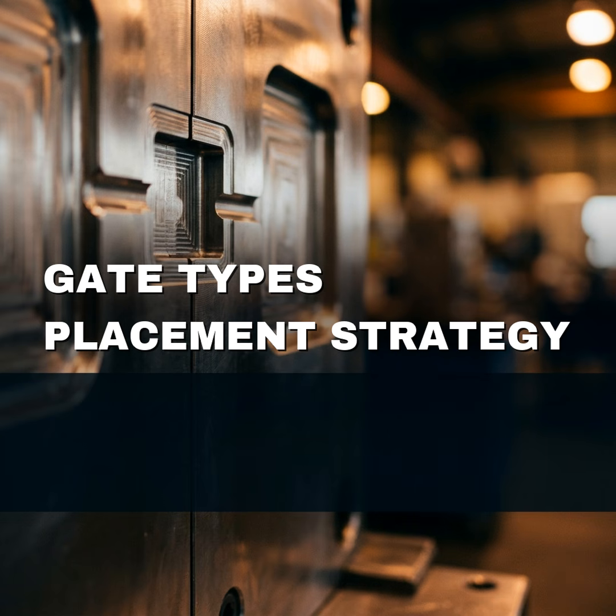We have the pinpoint gate, or just pin gate. This is a very widely used gate type, round in cross-section and quite small, typically 0.6 to 2.8 millimeters in diameter. Pin gates always sound like they'd be really precise. What's the appeal there? They offer a lot of location flexibility. They also allow for automatic gate removal, which is a huge plus for automation. You get reduced residual stress at the gate, and it solidifies faster. They're good for multi-cavity center feed molds and for low-viscosity plastics or those sensitive to shear rate.